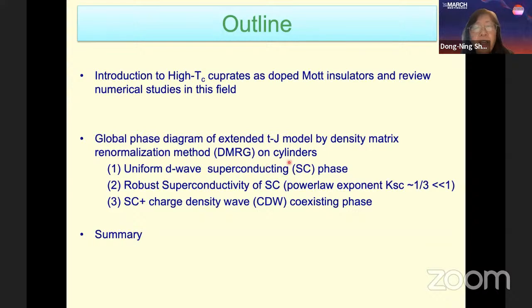Our study is based on the extended t-J model. We'll demonstrate a global phase diagram with different quantum phases, including a uniform D-wave superconducting phase, and that phase has robust superconductivity. In our quasi-1D system, the superconductivity demonstrates very slow decay in real space, with a power law exponent much smaller than 1.